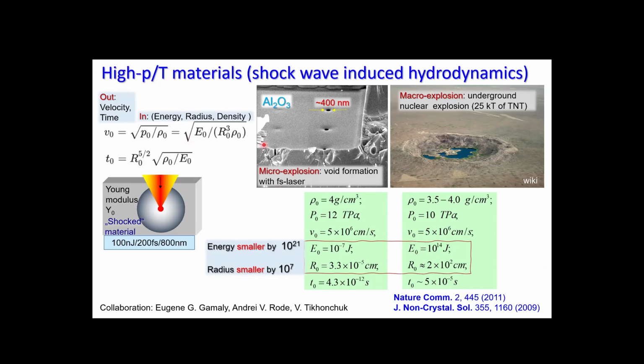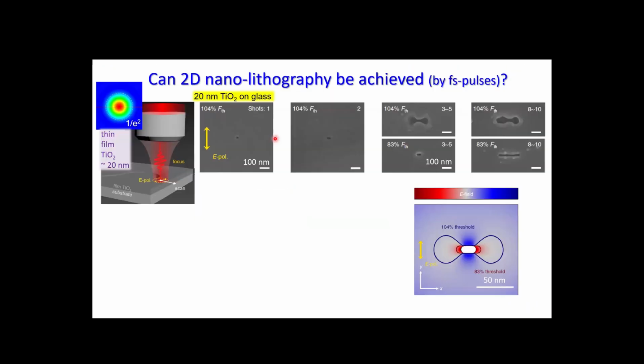The message here is that when we have this energy deposition, which is happening very shallowly because of ionization and breaking material into the absorbing volume inside a transparent dielectric, we can deposit energy very efficiently. But now back to lithography. We are interested not in the axial energy deposition, but in the lateral, how small things we can write on the plane. And here we are in the scenario where we are preparing a sample for lithography tasks.